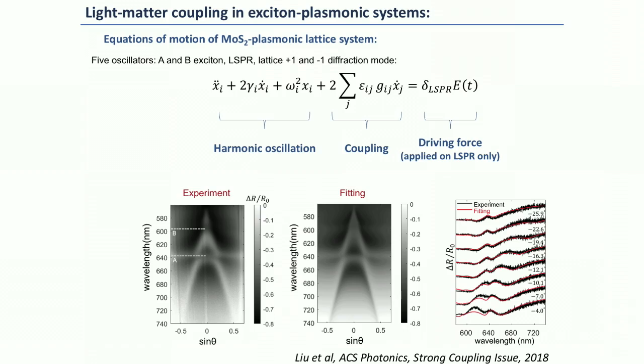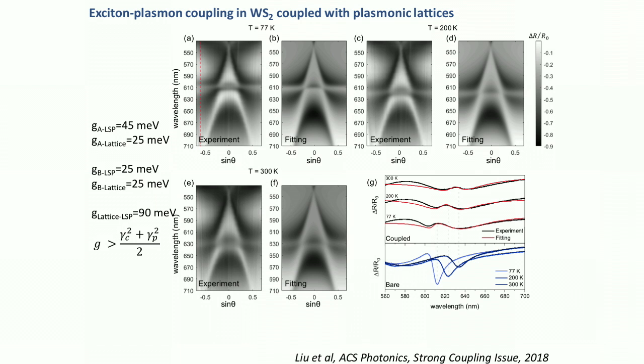So we came up with this equation of motion approach, which takes into account all the resonances and line shapes. The only input is the coupling strength. We solve this, and then fit to all the spectra that we get across all the angles. As you can see, we do a very good job using this model, and from there we can extract the line shapes of the coupled system. An interesting thing is that by solving this model, we can solve for the Fano line shape, which is the intermediate coupling regime, and the strong coupling regime, which is the polaritonic regime. So this shows that we've got things pretty much under good control.